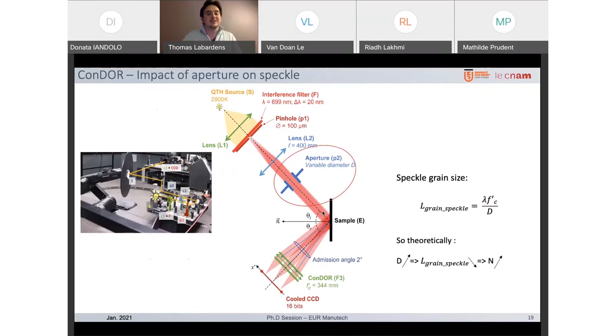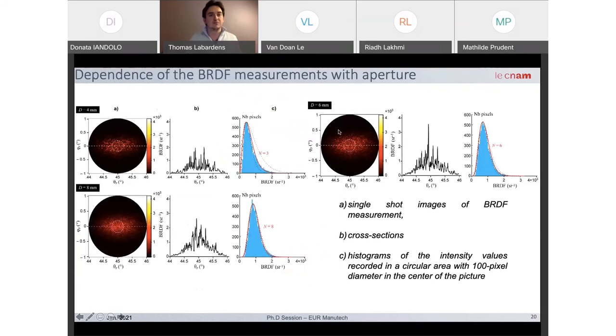We have here three different measurements, where you have single shot images, cross section, and the histogram of the intensity values recorded in a circular area in the center of the picture. Why do we look at this? Because we can see the probability distribution. And as we can see, when we increase the diameter, here we have d equals 4 millimeters, then 6 millimeters, and then 8 millimeters, the speckle grain size gets thinner, and the order of the gamma law gets higher. So this is quite coherent with the speckle theory.